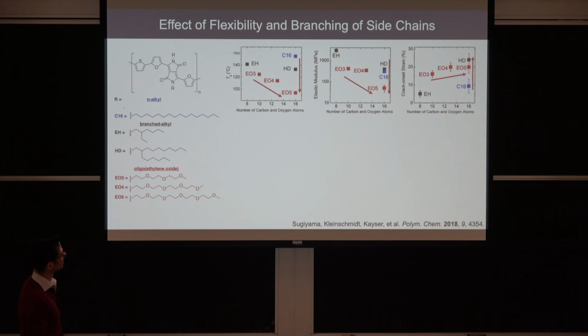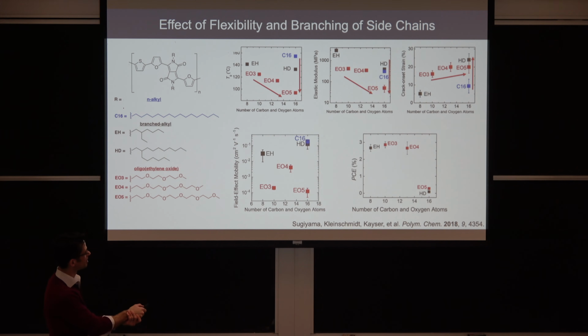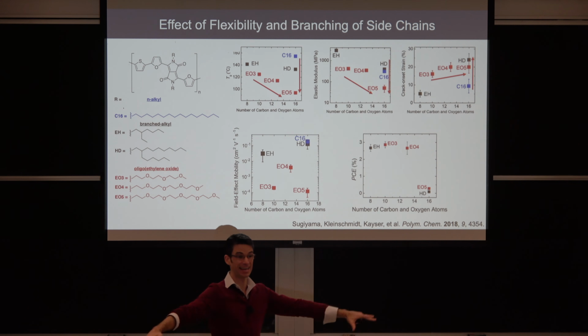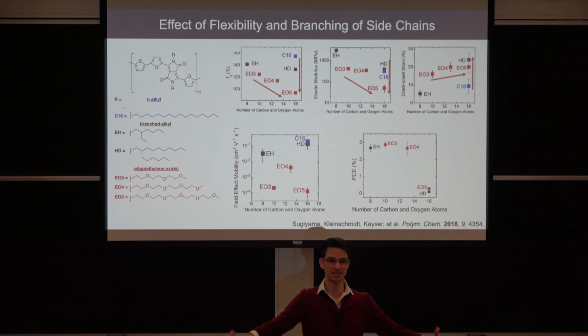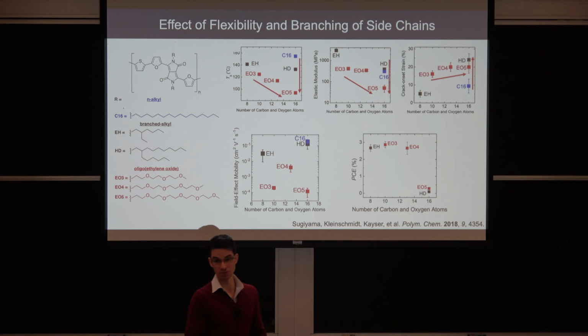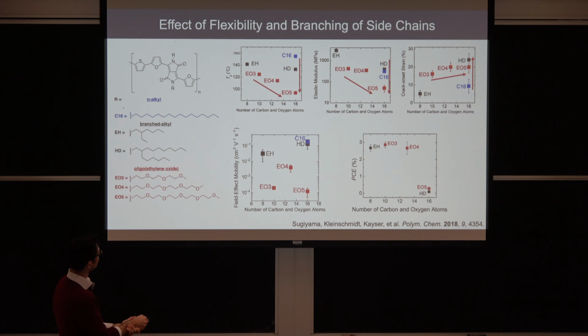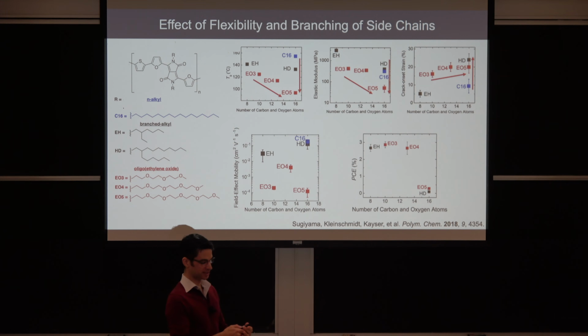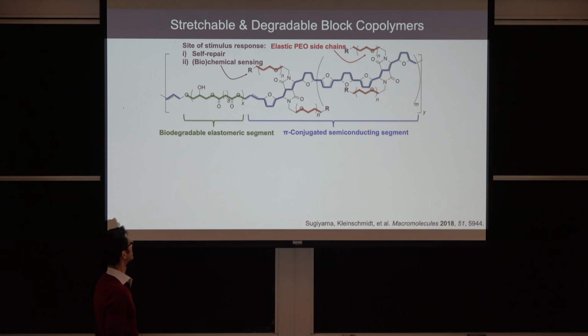And I want to get to another thing. So suffice it to say that if you have these ethylene oxide side chains, which are more flexible than these alkyl side chains, then the overall material tends to be less stiff and brittle and more deformable. Moreover, if you look at the field effect mobility in a transistor and the power conversion efficiency in a stretchable rubber solar cell, you can see that some of these materials, like this EO4, tend to give you the best of both worlds in deformability and charge transport properties.